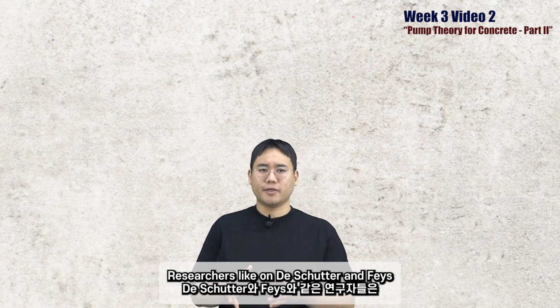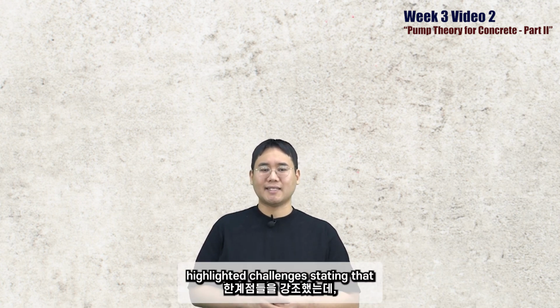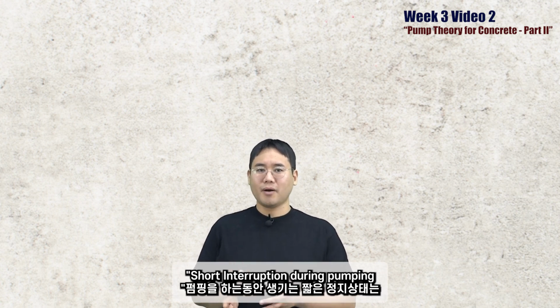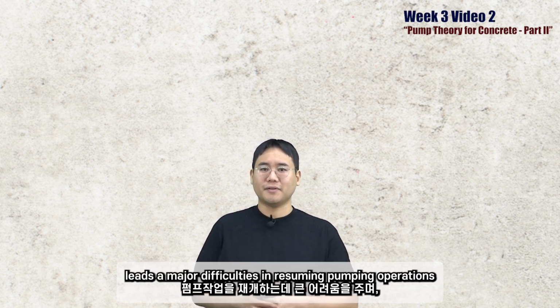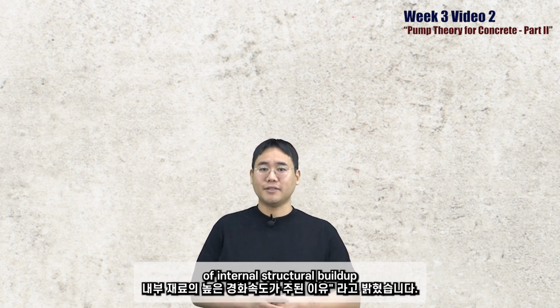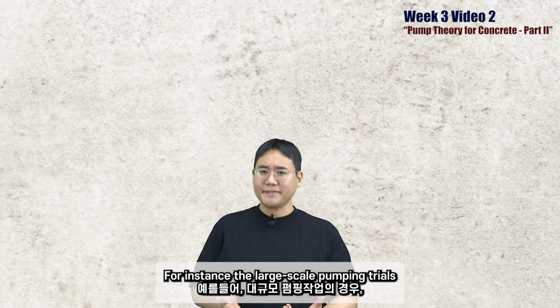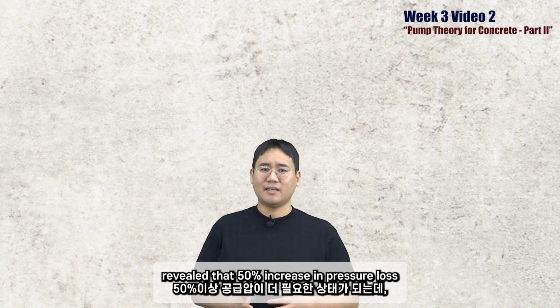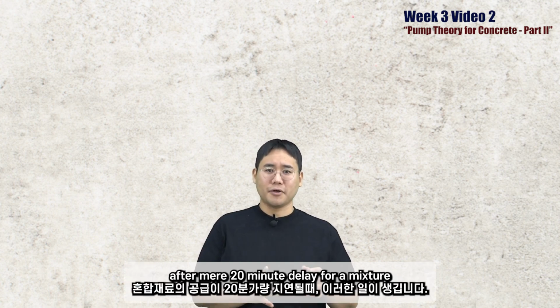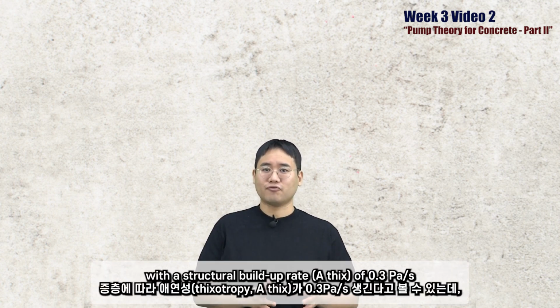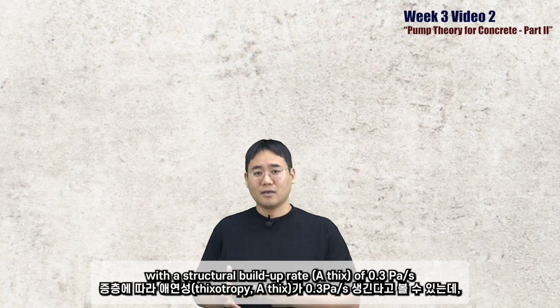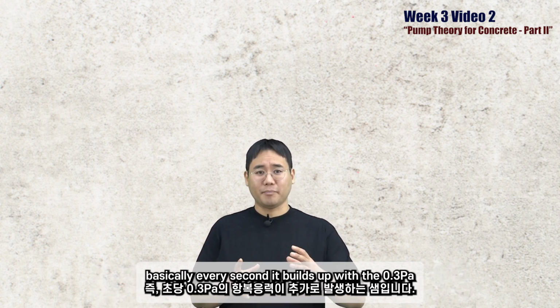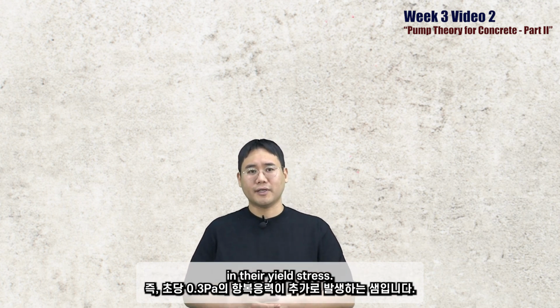Researchers like De Schutter and Feys highlighted the challenges, stating that short interruptions during pumping lead to major difficulties in resuming pumping operations due to the sometimes tremendous effect of internal structure buildup. For instance, large-scale pumping trials revealed a 50% increase in pressure loss after a mere 20-minute delay for a mixture with a structural buildup rate, Athix, of 0.3 pascals per second. Basically, every second it builds up 0.3 pascals in its yield stress.